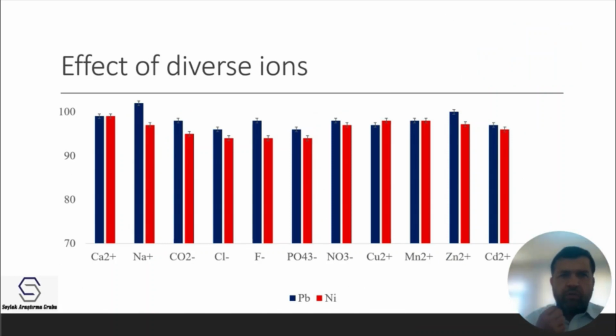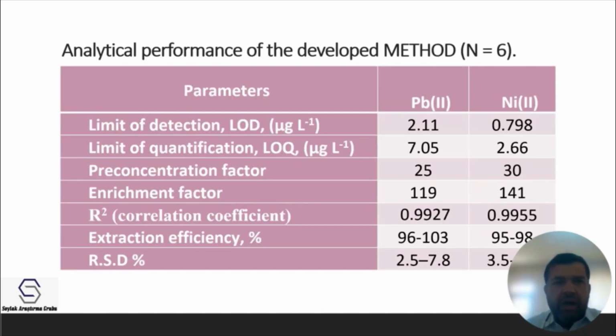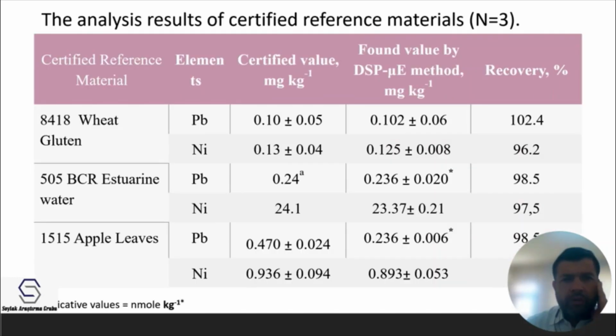This slide shows the effect of interfering ions on the developed method. During the determination of lead and nickel, recoveries were found greater than 95%, which indicates there is no interference present during analysis, and the developed method is selective and suitable for lead and nickel determination. After determining the optimal conditions, we calculated analytical figures of merit of the developed method: limit of detection, limit of quantification, pre-concentration factor, enrichment factor, extraction efficiency, and relative standard deviation of the method. For the validation of the proposed method, we used a certified reference material, and the obtained data show excellent correlation with the certified values at a 97.5 to 102.4% confidence level.